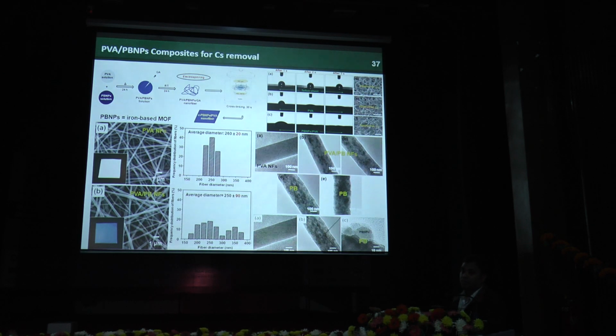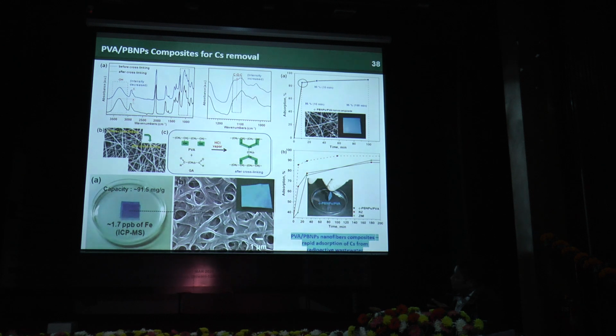And also for radioactive pollutants, we developed PVA nanofiber with some functional materials, iron-based functional material. We incorporated it and we cross-linked it in order to get high stability. Because PVA is water soluble, when you go for removal of some radioactive species from industry wastewater, the fiber will be dissolved. So in order to achieve stability, we cross-linked it. You can see this is a pure PVA nanofiber, and inside the functional materials are incorporated successfully. And these are some spectroscopic results to confirm the successful cross-linking of PVA nanofiber.